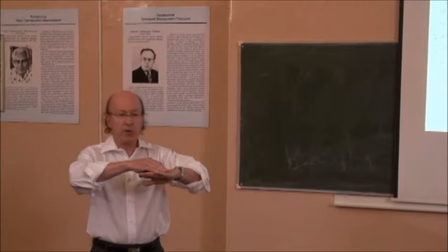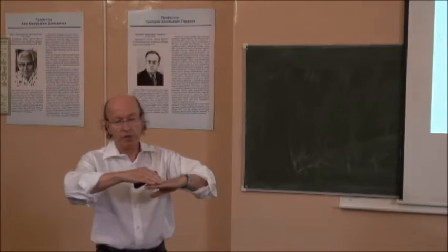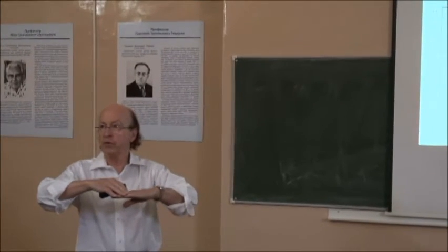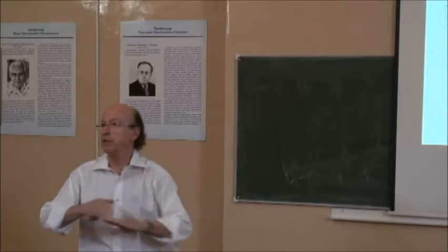So here the time to travel is proportional to the radius. And of course, since the velocity is constant, the distance also is proportional to the radius, and you see that it's always proportional to the radius with a prefactor on the order of 1, that's 1.5. And that's nearly the same value on cyclohexane and benzene, on the order of 1.5. And I told you, once the drop has gone from the place where it was at the melting temperature, it is on a colder temperature and the layer is so thin that it freezes immediately.